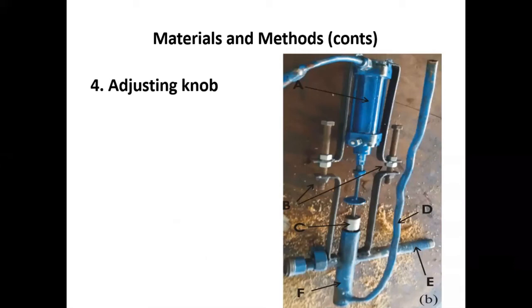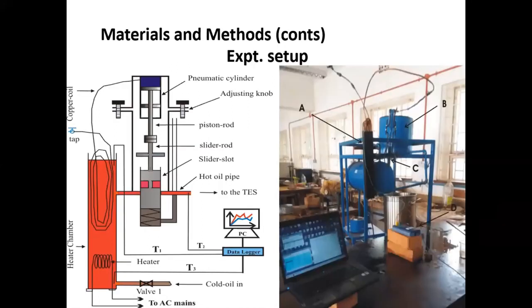So the fully assembled experimental setup is as shown there. If I follow the schematic diagram to the experimental setup, we have the cold oil which comes in through valve 1. When valve 1 is open, and then in the heating chamber, this oil will get heated, where hot oil always rises to the top. When it is at the top, it is in contact with the copper coil, so the oil in the copper coil will also get heated.